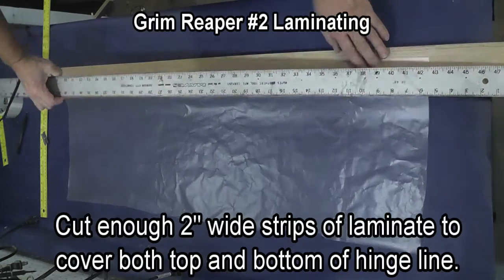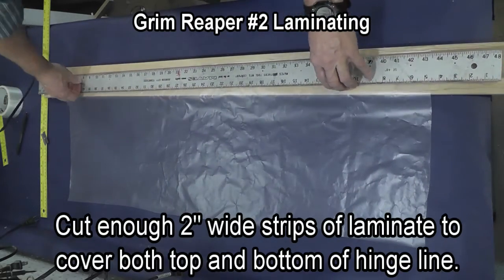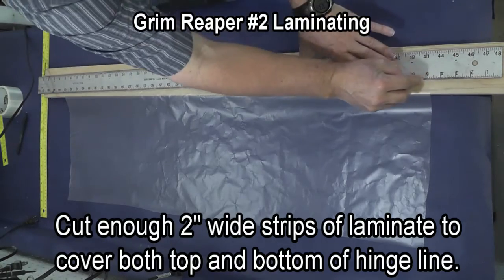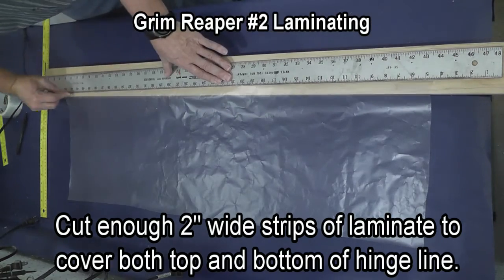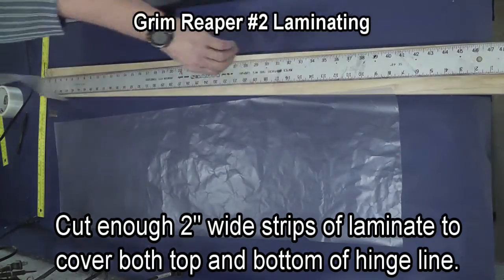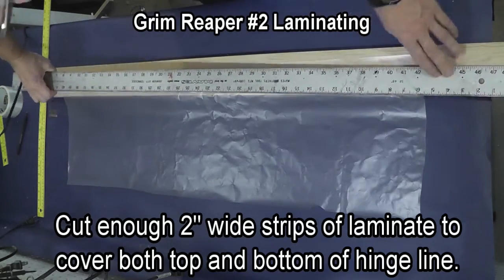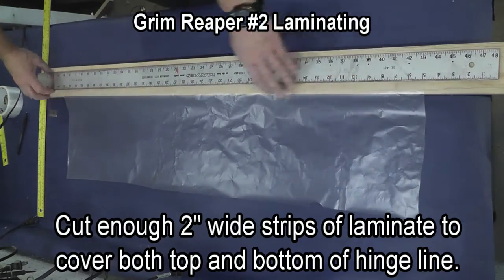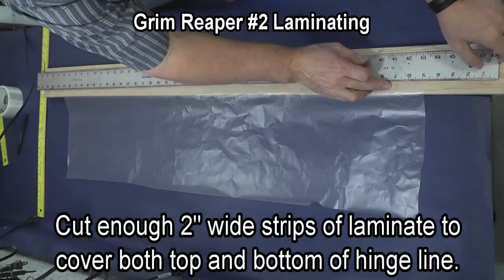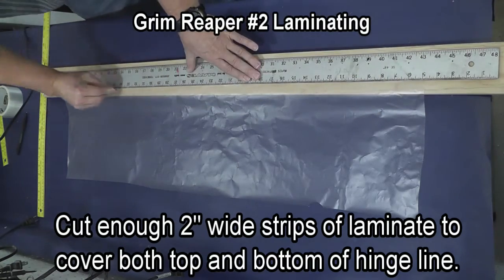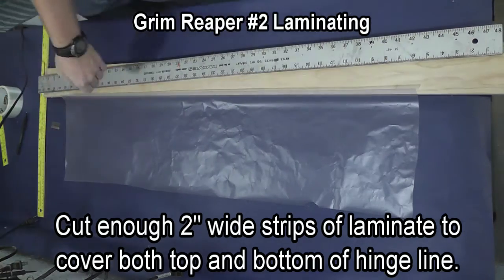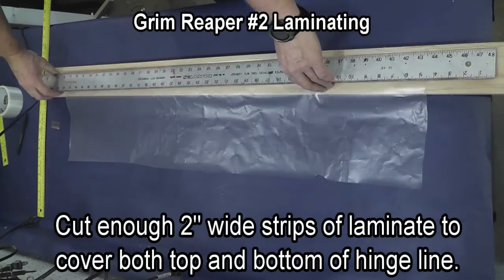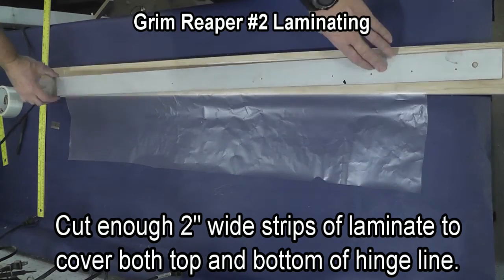And then after you have got the tape on, we're going to put some laminate over the top of the tape. The tape does not take UV light well, and it will turn yellow and the adhesive will fail within a few months if you don't put laminate over the top. The laminate that is in the kit has a UV protection in it that protects your plane from sunlight.